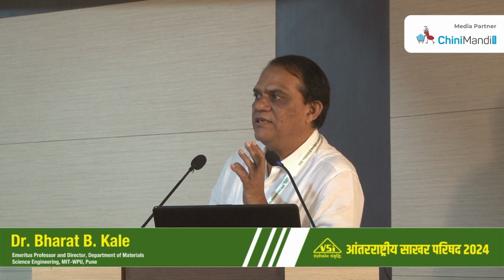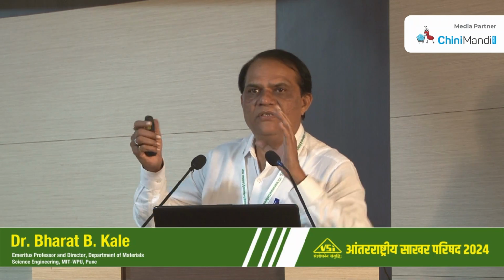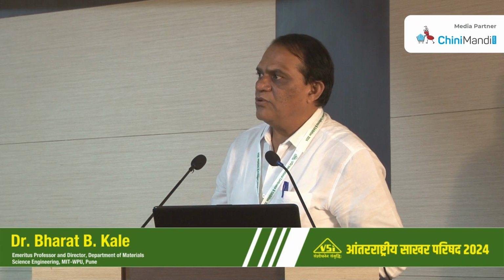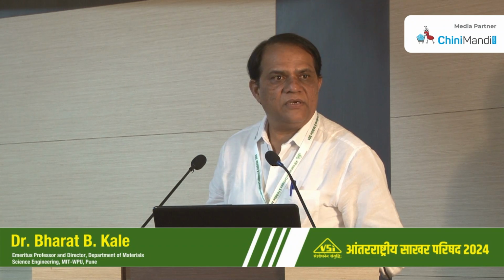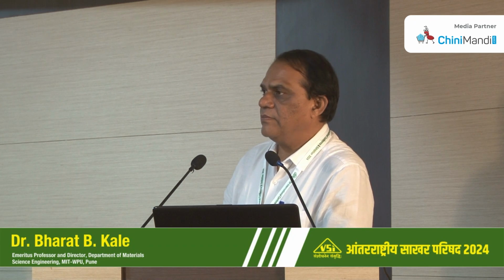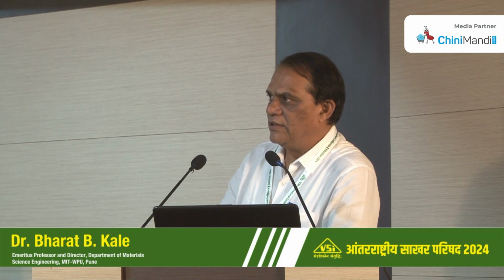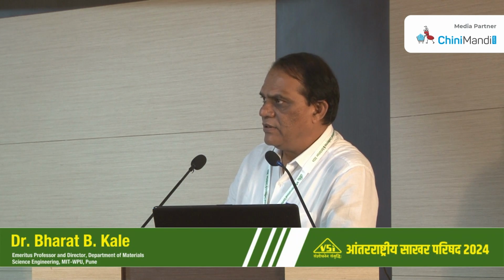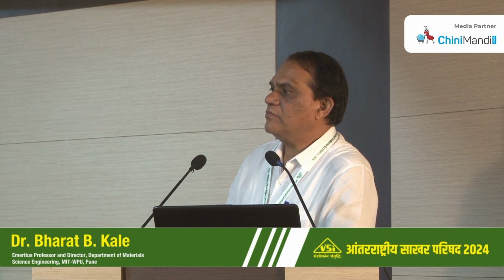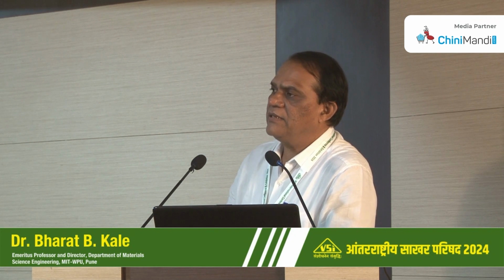See? And they are highly dispersed. Actually the Ag3PO4 structure, if you see, is a dodecahedron, a big dodecahedron, maybe 1 micron to 2 micron size. But in the glass, you will get almost 4 to 5 nanometer or 6 nanometer, the same shape. So this is the beauty of this process. Initially, you can see the reflectance of this Ag3PO4 is only up to 600 nanometer. But see the absorption, it is enhanced up to 500 to 600 nanometer. That helps a lot for the photo excitation process.